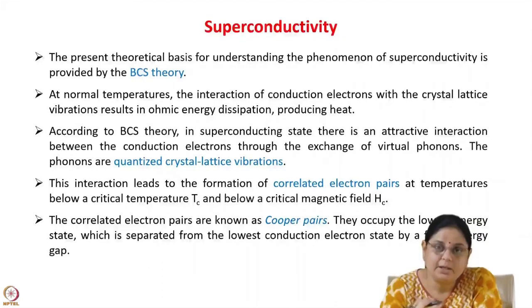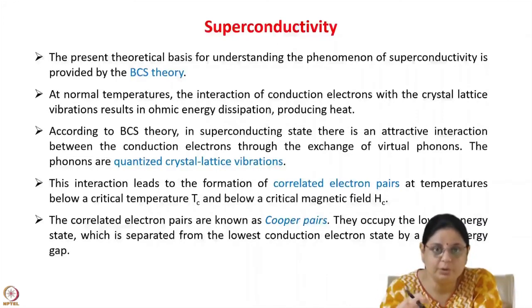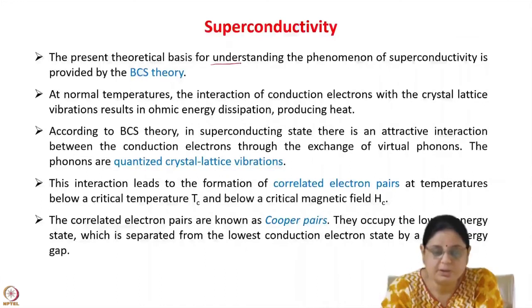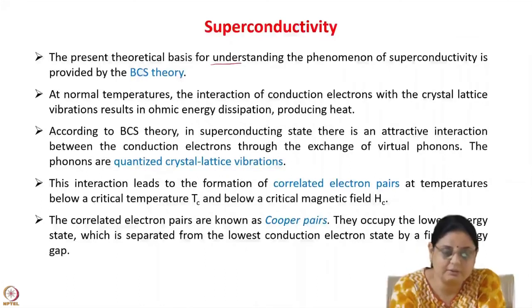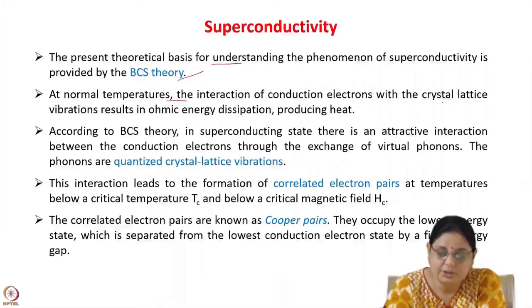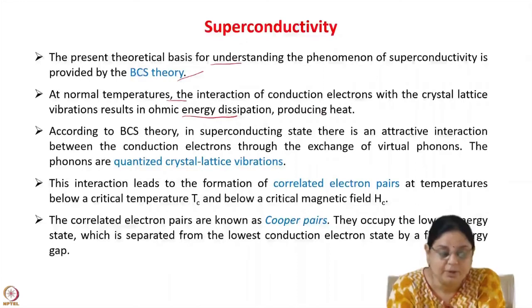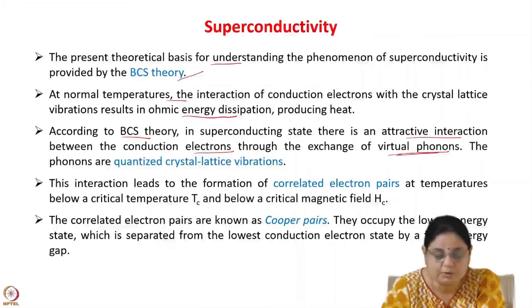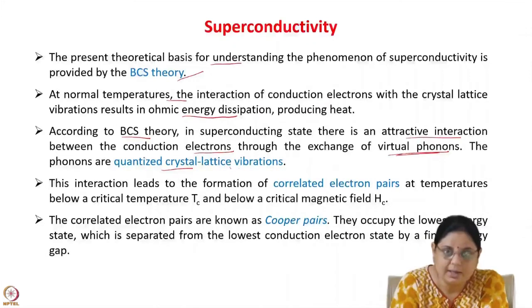That is how superconducting cavities come into picture. Before we understand superconducting cavities, let us get a brief overview of superconductivity as we know it today. The present theoretical basis for understanding superconductivity is provided by BCS theory, given by three scientists: Bardeen, Cooper, and Schrieffer. At normal temperatures, the interaction of conduction electrons with crystal lattice vibrations results in ohmic energy dissipation, producing heat. In the superconducting state, according to BCS theory, there is an attractive interaction between conduction electrons through exchange of virtual phonons — quantized crystal lattice vibrations.